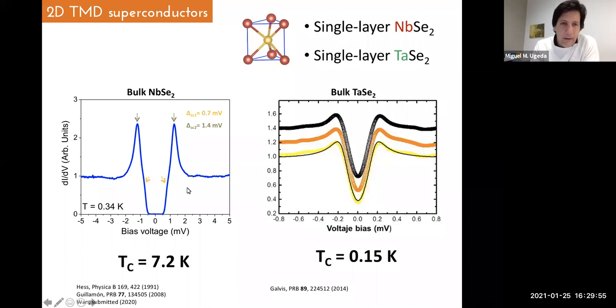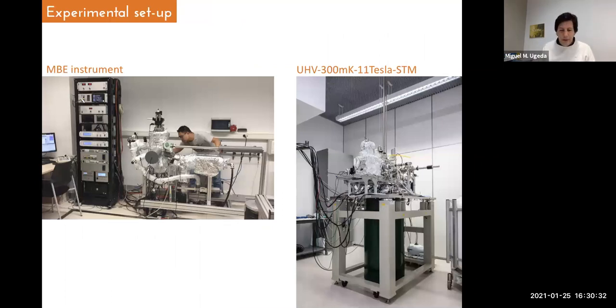We know well that at least for niobium diselenide, this material in bulk has two different gaps. It's a multi-gap material. Here you can see the first one with a width of 0.7 millielectron volts and the larger one with 1.4 millielectron volts. Experimentally, this is nothing that we can tell in tantalum diselenide. Probably it is similar, but I think experimentally it's not proved that it's also a multiband superconductor. Okay, so let me now start with our experimental results.